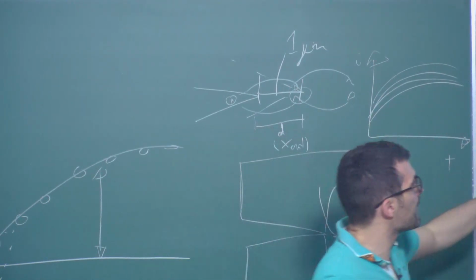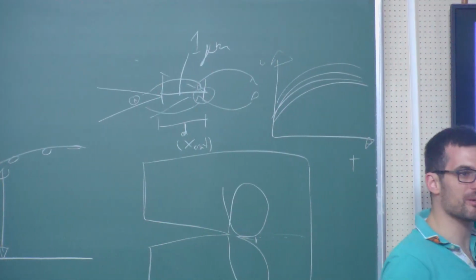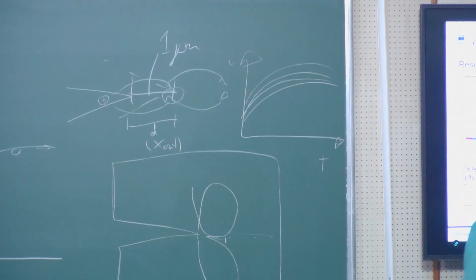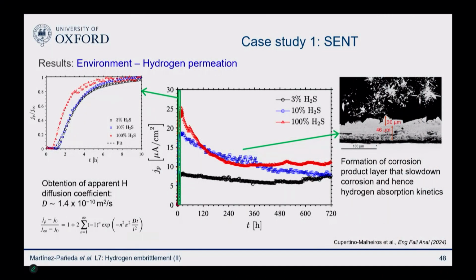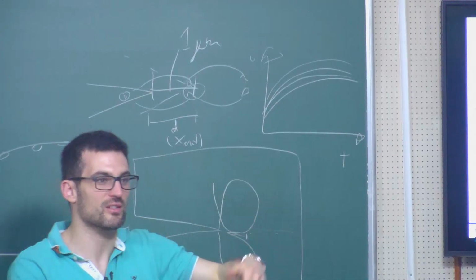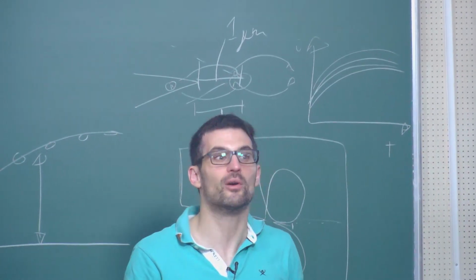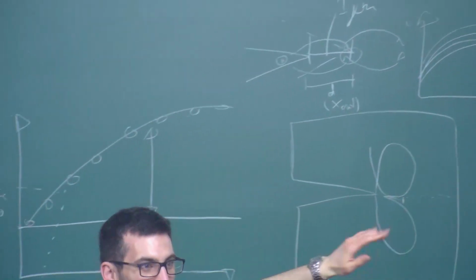But here, you do get the steady state, but then something happens. You form these corrosion products, and things go down. So the hydrogen that you have in your surface must be going down, because on the exit surface where you measure things, you don't see hydrogen coming out. So the hydrogen is not entering your metal for some reason, or it's less and less entering.